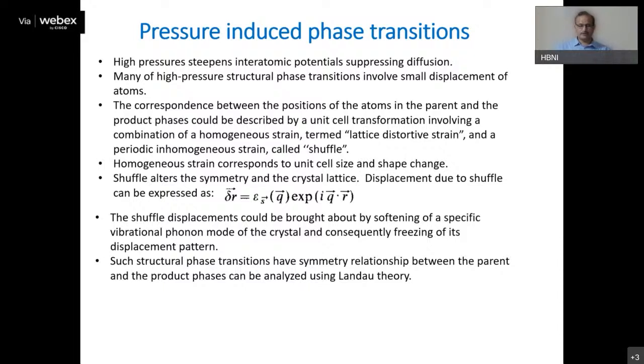Just like martensitic phase transitions, there can be two kinds of coordinated motion, or movement of atoms. One is the lattice distortive strain, which corresponds to the dilatation or distortion of the entire unit cell. This can be a homogeneous strain, and then there is a possibility that there can be shuffle. If you have a unit cell with more than one basis, and there is some relative movement between these bases and it freezes to some position, then this corresponds to the shuffle kind of strain. So your phase transition can correspond purely to the homogeneous strain, or purely to the shuffle, or maybe a combination of these two.